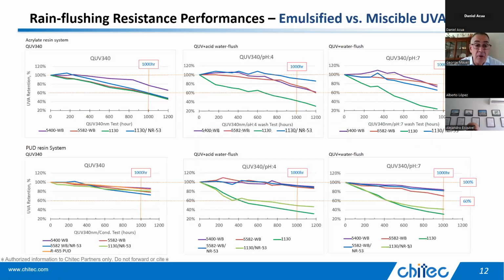Now, we did some follow-up tests and some different systems. The top one here is an acrylic. And you can see in this particular one, we're tailing off on the 1130, it's pretty bad, this green line. And then down below in the polyurethane dispersion, we're seeing the 1130 is quite a bit weaker. And the ones that don't hydrolyze or get extracted are really performing quite a bit better.